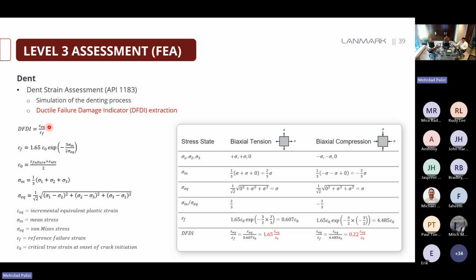The demand is similarly equivalent plastic strain. The capacity is something called fracture strain. Fracture strain is coming from this relationship. As you can see here, we have some consideration for the stress triaxiality. And we also have this epsilon 0. This is the critical true strain at the start of the crack initiation. Its value is between 0.3 and 0.6, according to API 1183.